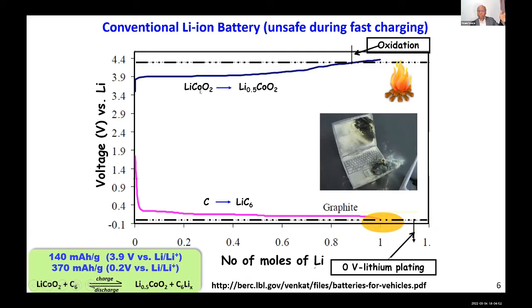If you take a lithium cobalt oxide versus graphite, when you are charging, what happens is you are removing lithium, and this is the extraction of the lithium from lithium cobalt oxide. This potential is somewhere about 4 volt versus 0. 0 is the lithium. That is my reference. You can see here the lithium is taken as a reference. So versus 0, this is happening at about 4 volt or so.